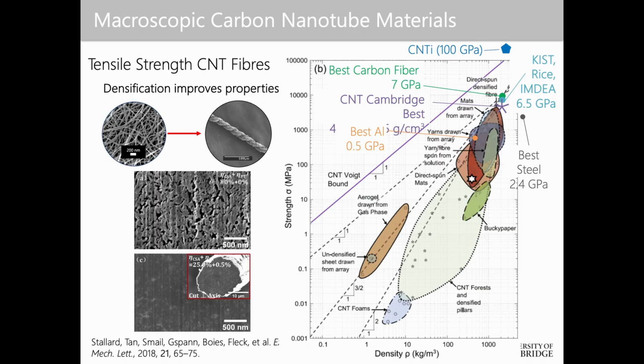And so what has led to this ultimate improvement? It's fundamentally taking a material that is very disorganized, carbon nanotubes, and organizing them in a way where their properties are aligned with one another and they're sharing the load, so to speak. And so I'll talk a lot about what that means. But basically what we get out of the reactor, and I'll spend more time talking about what these reactors look like, is something fairly isotropic, and you might think of isotropic as another way of saying disorganized, equally dispersed in all directions. And these are bundles of nanotubes. And if we organize them and densify them, we basically move along the plot to the right, and that pushes our material properties up and to the right as well.